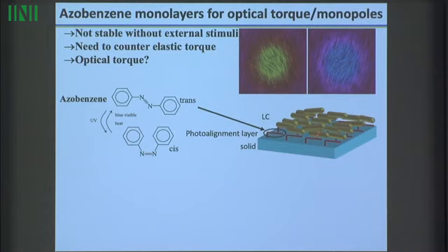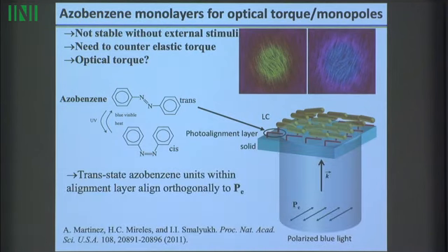And so in this case, we will use azobenzene dye molecules that are highly responsive to light. And in liquid crystals, including the liquid crystal industry, these types of azobenzene molecules have been used for a while to align liquid crystals on surfaces, because as we shine linearly polarized light on this surface, these azobenzene moieties will align perpendicular to the linear polarization of light. And so that allows them to align liquid crystal molecules parallel to the azobenzene molecules, and with light you can control that alignment.